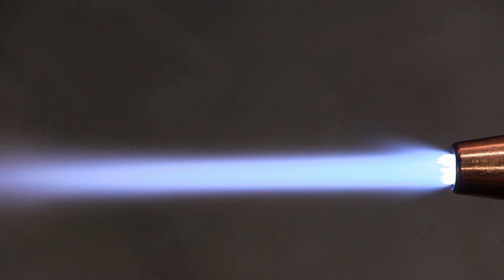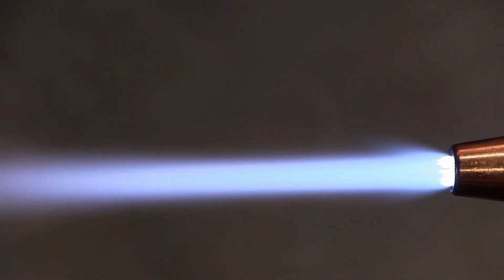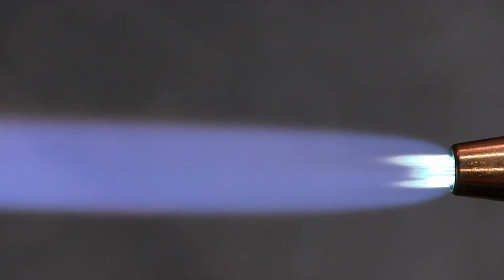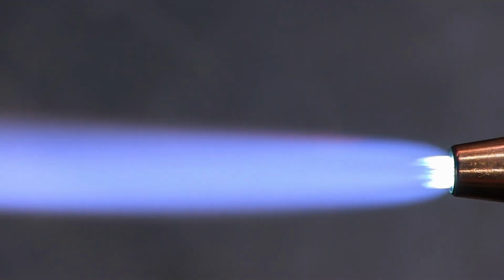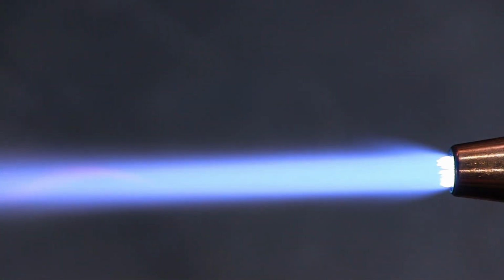You can see everything becomes very clear, and the core of the flame, the brightest part right in there, is very, very crisp and very, very sharp. In this case, the flame has far too much oxygen, so not all the oxygen burns through. When you cut plate with a flame like this, it actually oxidizes the steel a little bit. So you need to find the balance somewhere in between.